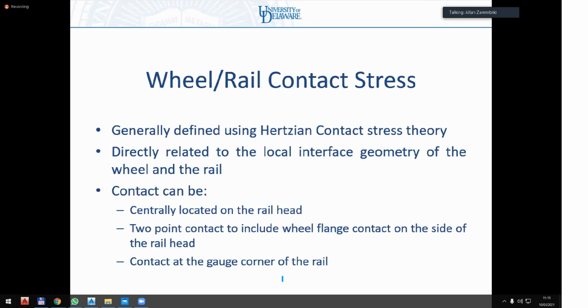So what we're doing here is we're trying to look at the wheel rail contact stress, which is everything we've been showing you up until now. This is my wheel rail contact stress. It's usually defined using Hertzian contact stress theory, the most commonly used theory for wheel-rail contact. It's directly related to the local interface geometry between the wheel and the rail, to include, among other things, the radius of the top head of the rail, the radius of the wheel, the radius of the transition zones in the rail. All of this directly relates to the shape and size and magnitude of the wheel-rail contact zone, which in turn affects the magnitude of the stress.